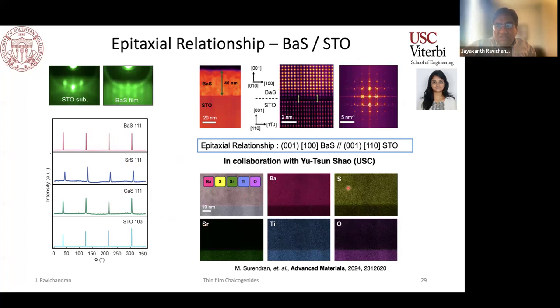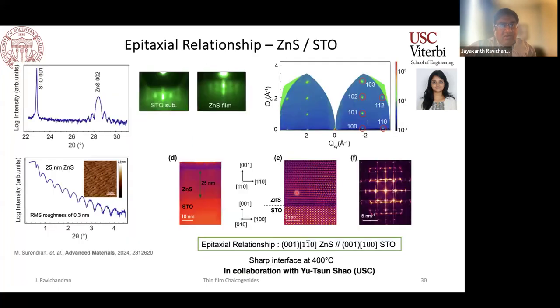So we collaborated with Yu-Tsun Shao, where he did all this STEM imaging and also EDS to check the composition. They seem fairly uniformly distributed. And we looked at the growth of zinc sulfide. Zinc sulfide is a material that many people have grown along the years using a variety of techniques. In our case, we could get a reasonably high quality zinc sulfide even down to 300 degrees Celsius, with fairly sharp interfaces when you grow at 400 degrees Celsius.